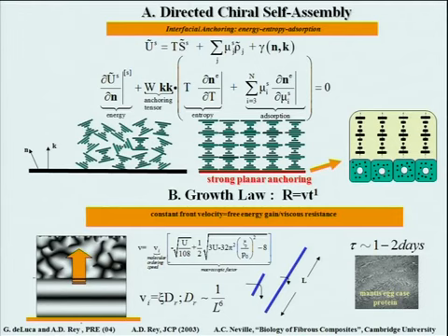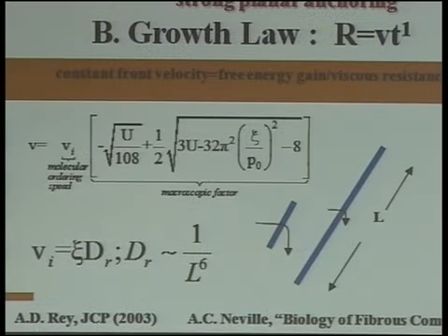You work out this expression of propagating front between cholesteric and nematic. The Landau-de Gennes equation gives you a constant velocity, which is a function of concentration, inversely proportional to the pitch. So the pitch resists the growth. And this intrinsic speed, if you will, is the characteristic internal length in the system, which is nanoscale, which is just the square root of Frank elasticity over kT. And this is the rotational diffusivity for this rod.